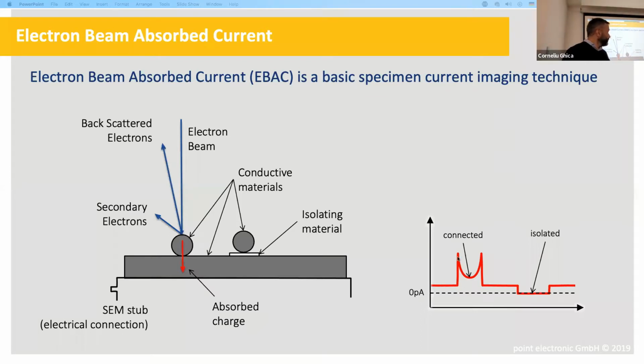There will be some topography information because at the very edge of the particle we'll have secondary electrons produced and absorbed and so on, and the yield of SE and BSE changes. And when we have an isolated particle, we will read zero current. This is an important aspect of the technique: we don't say it's just black or dark. We can actually measure the current and say it's zero. So it's a quantitative technique in that sense, because we know how much the signal is.